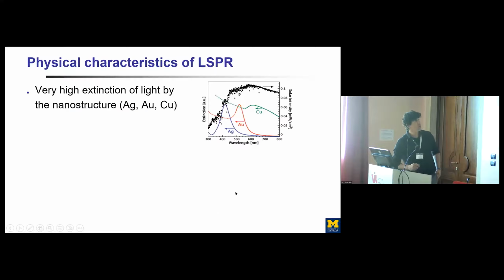So for example, nanoparticles of silver, gold, and copper exhibit this surface plasmon resonance at conditions that are consistent with UV-visible light, basically with solar applications. So if you have solar light, you can excite this surface plasmon resonance on silver, gold, and copper. And I show here an extinction spectrum for a collection of silver, gold, and copper particles as a function of wavelength. And you see this extinction, which is taking place at these wavelengths for these nanoparticles.